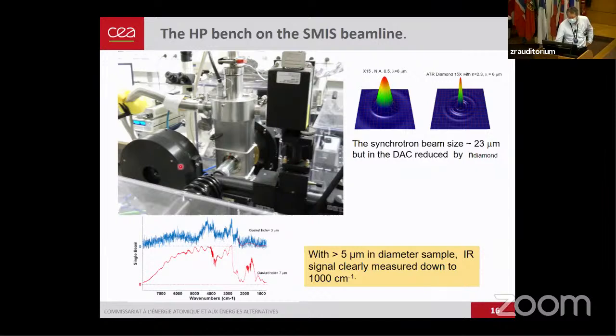We have two reflective objectives of large frontal distance, and the infrared beam is 25 micron, very bright, as on synchrotrons. And if you go inside the diamond, it's even reduced by the index of diamond in this cell. The important point is that you can have a very nice infrared signal, even with a 5 micron diameter sample. You have to know that we are probing the range roughly 8,000 wave numbers to 1,000 wave numbers. It is 10 micron, so you are at more than the limit of diffraction for your small sample, but you still can make a lot of nice measurements.